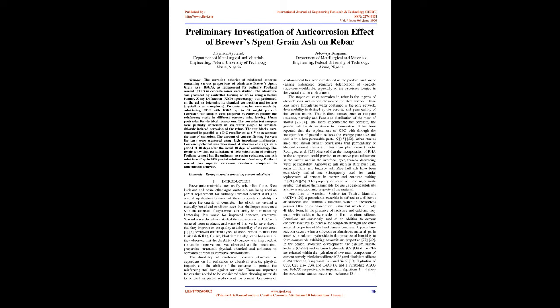The test blocks were connected in parallel to a DC rectifier set at 6V to accentuate the rate of corrosion. The amount of current flowing between the bars were measured using high impedance multimeter. Corrosion potential was determined at intervals of 2 days for a period of 28 days after the initial 28 days of conditioning.